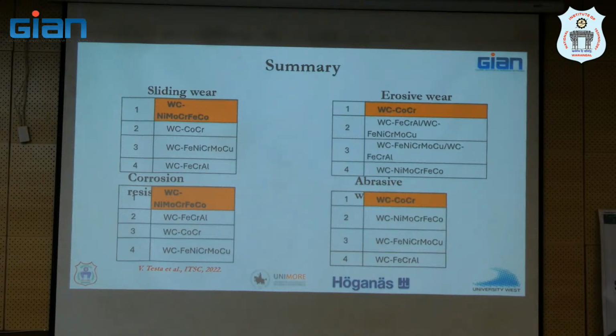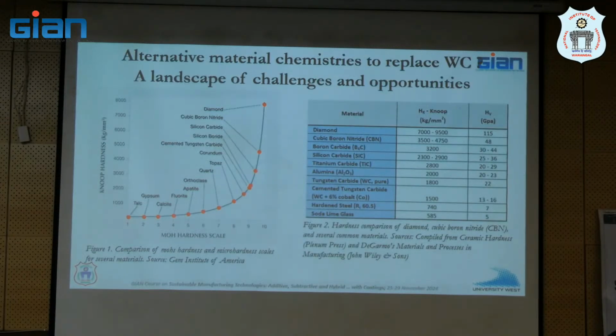But this is a summary. It's a great way to get rid of cobalt. Yeah, there are good ways to do that. What about tungsten carbide? If I look at tungsten carbide on the Mohs scale or the hardness scale, I find there are many materials above tungsten carbide. All of these, for example. Why can't we spray those? Why are we stuck with tungsten carbide? Because all of these are conventionally very hard to spray. They tend to degrade thermally much faster than tungsten carbide.